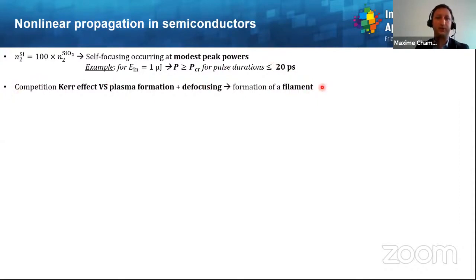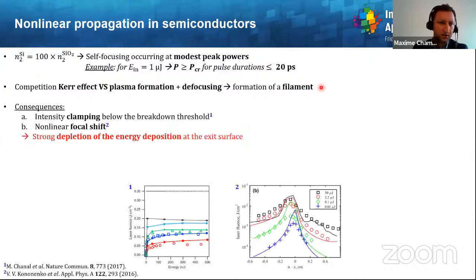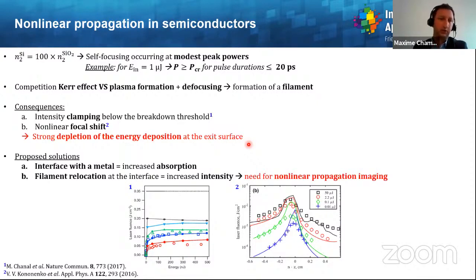And thus, as previously described, there will be this competition between Kerr effect and plasma formation together with defocusing, leading to the formation of a filament. Then the two consequences, I already talked about this. Again, there is a strong depletion of the energy deposition at the exit surface of silicon, so actually the interface between silicon and copper in our case. So the solutions we propose are, first, we use an interface with a metal, meaning that the absorption will be drastically increased, which is pretty good. And second, we propose a filament relocation method to get an increased intensity at the interface between silicon and copper. But to do so, we need nonlinear propagation imaging, and this is exactly what we did.